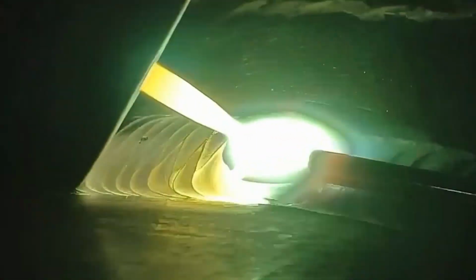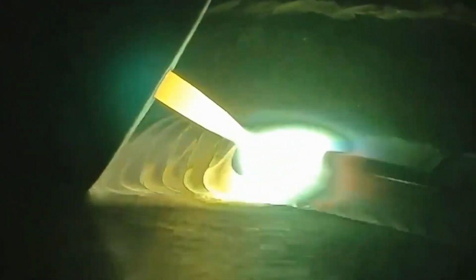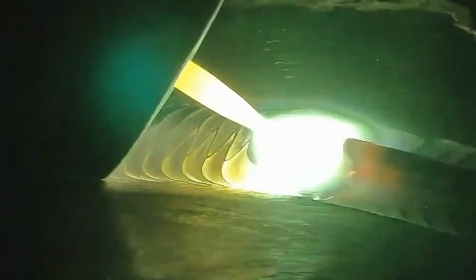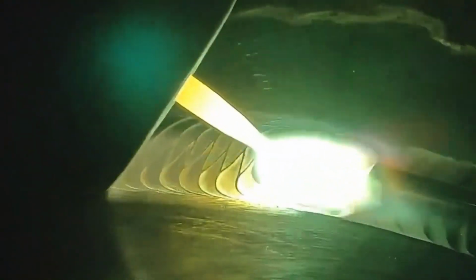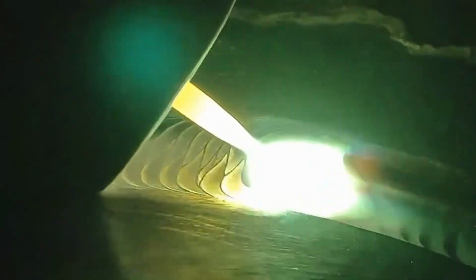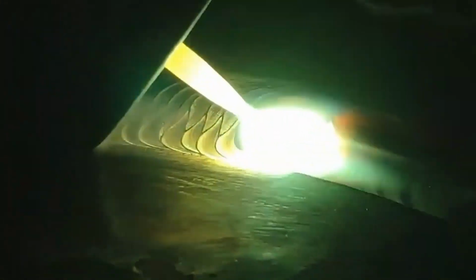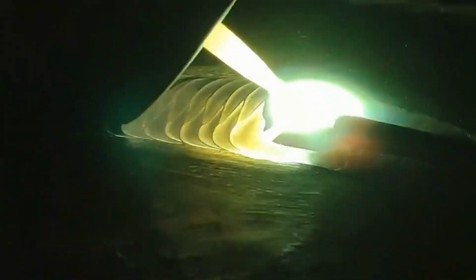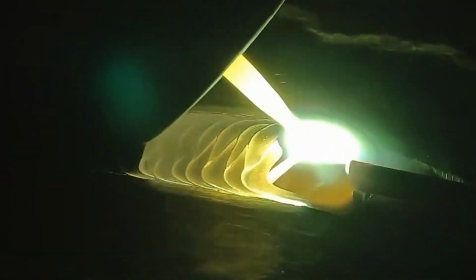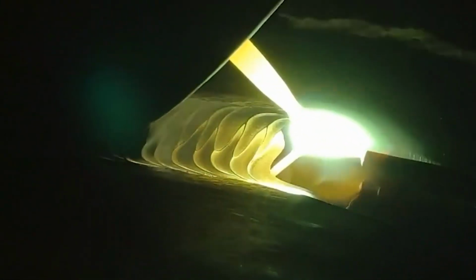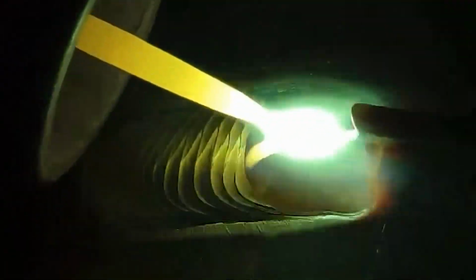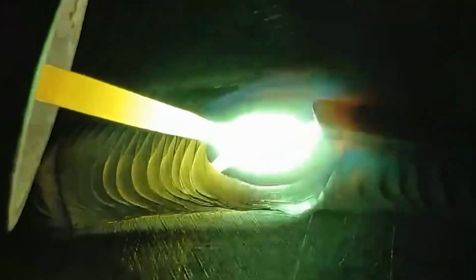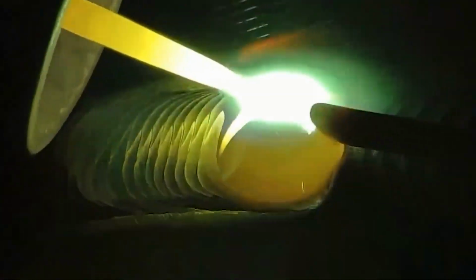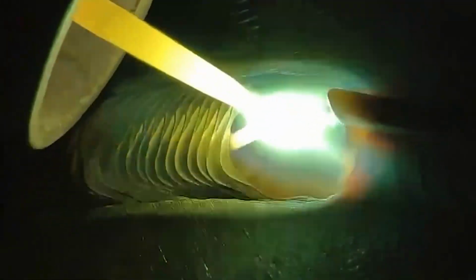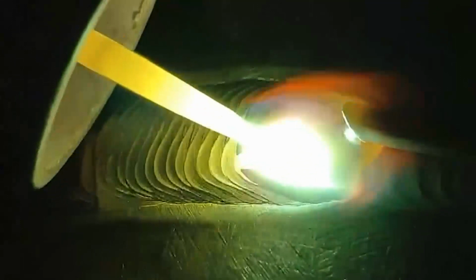The local error value of butt single-sided welding should not exceed 10% of the wall thickness and not more than 1 millimeter. For the counterpart, the oil, paint, scale, and oxide layer on the surface of the weld and the 15mm side of the base metal should be cleaned until the metallic luster is exposed, and the groove surface should be inspected. There should be no cracks, heavy skin, or defects such as brush and groove damage. If the design requires it, penetration testing should also be carried out on the groove surface.